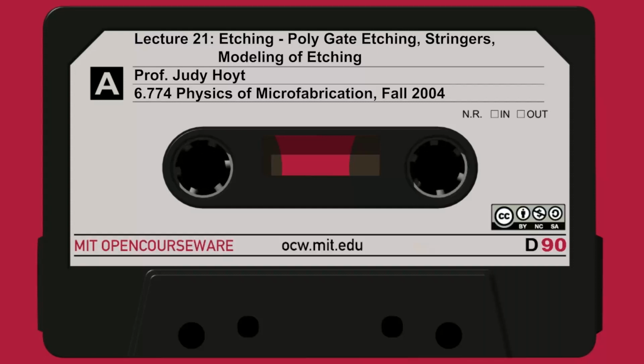This was formed by depositing nickel and reacting it at 450 all the way to the bottom. So there's no polysilicon left. Because these days, people don't want polysilicon gates. Polysilicon is a great material to etch. It's highly compatible chemically with oxide, but it has gate depletion problems. It doesn't have enough carriers in it. What's the highest you can dope polysilicon? Well, maybe 1 to 5 times 10 to the 20. So that limits your resistivity and it limits your gate depletion.